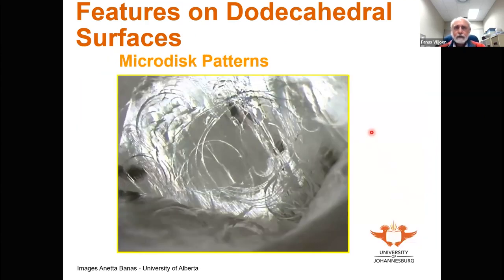And then very typical of diamonds from root zones of kimberlites, which is in a magmatic environment, as well as diamonds from dikes, where you can see these circular features, which are known as microdisc patterns. We think that in these root zones and in dikes, there is an abundance of volatiles exsolving from those root zones as they are cooling down. And in that case, these gas bubbles that form within the cooling kimberlite also serve to protect the surface of diamonds from resorption. And so even though there is resorption, you do see these microdisc patterns.